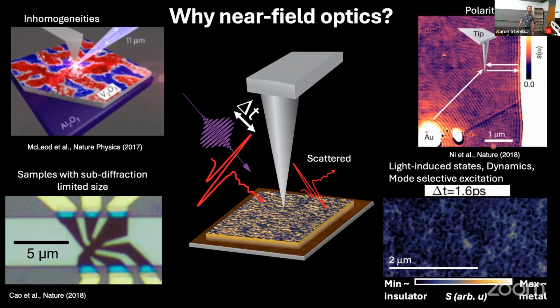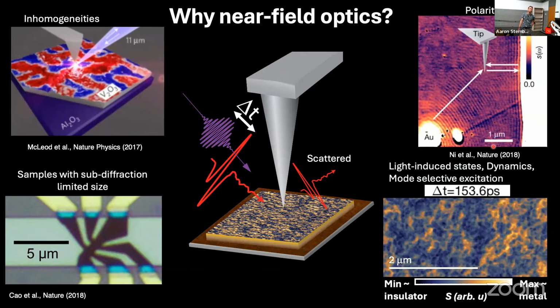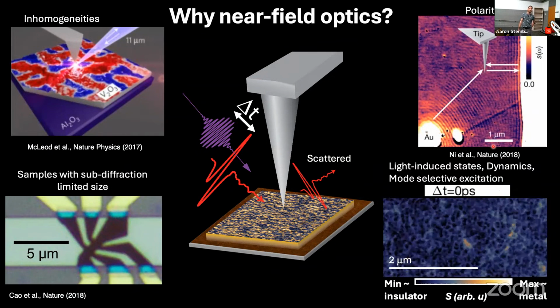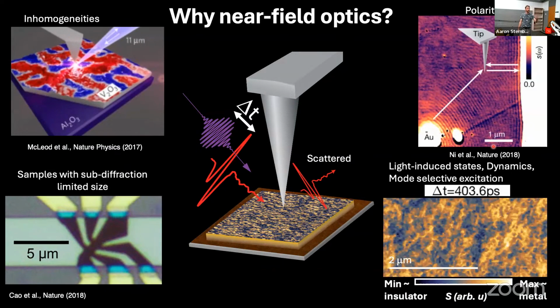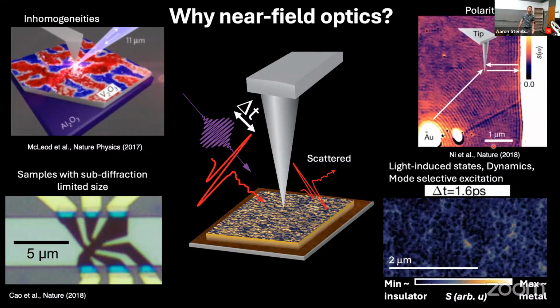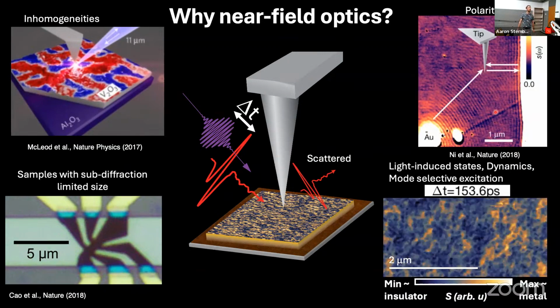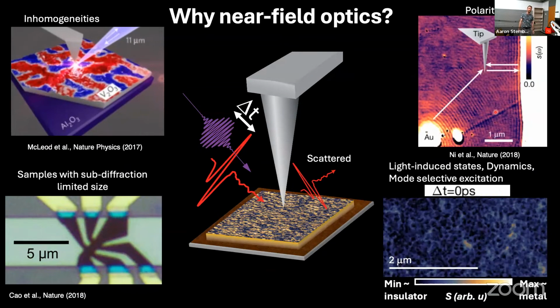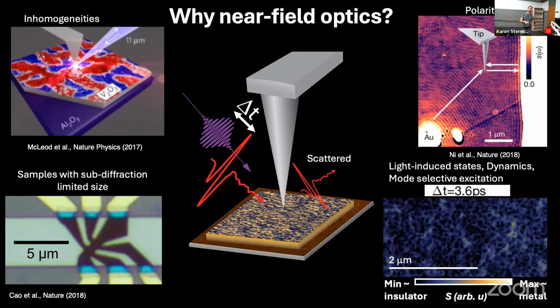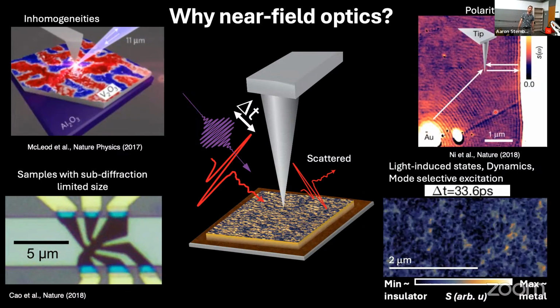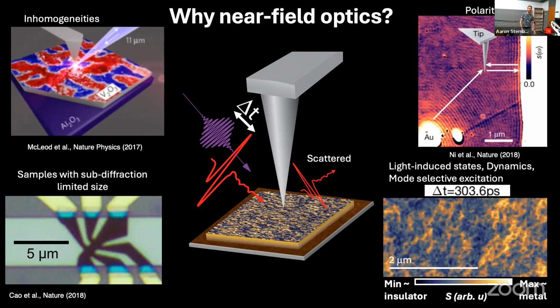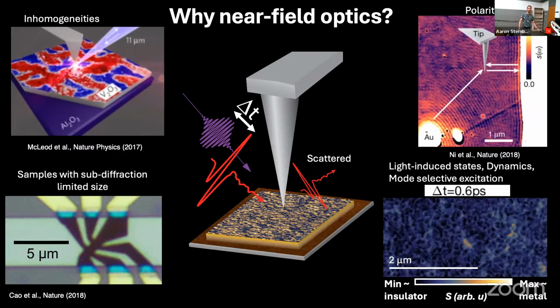So I think of this as a cavity. The resonant frequencies are determined by the position of the tip, and then you get resonant excitation of that cavity. And that's by mapping that signal into the spatial profile where the tip is. Yes, and that's how that map is generated. Essentially, yes. And in systems where the size of the material that is hosting this wave is confined or limited, then you can actually see specific cavity modes emerging. In this case, the sample is semi-infinite, and so it's really just the two objects that are creating the cavity.